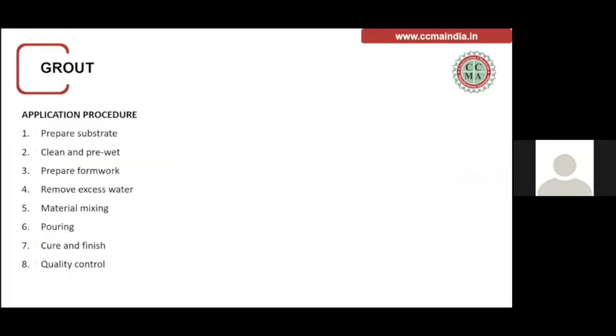Some application procedures. First, the substrate has to be prepared. As you see, these precast panels are constructed at a factory. They are kept for a long duration for curing. Then they are transported. So definitely during this period, till the time the joints and connections are filled, the surface becomes absorbent. So we have to ensure that these precast panels are in SSD condition during the grouting application, so that they do not suck water from the grout material. In case the surface is highly absorbent and water is sucked, there would be problems at a later stage. So cleaning and pre-wetting is one of the important parts of the grouting application.